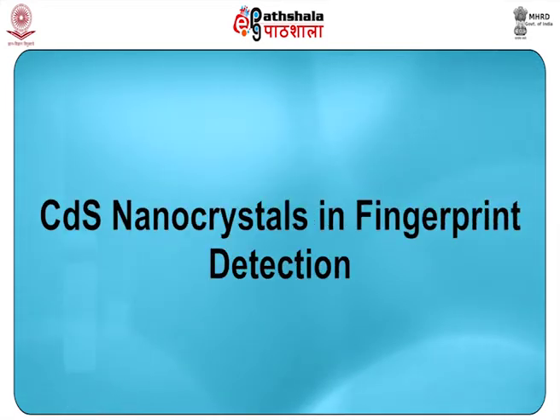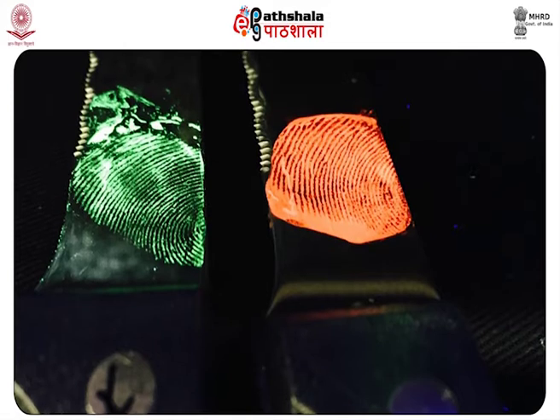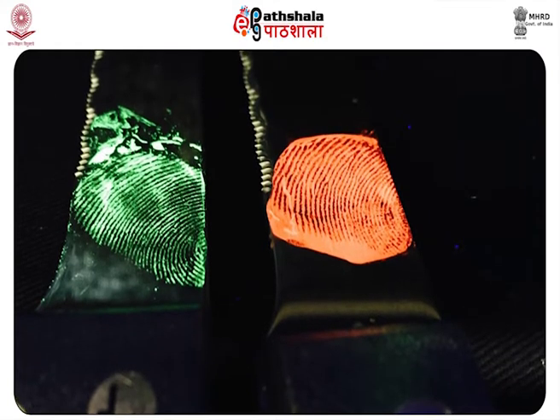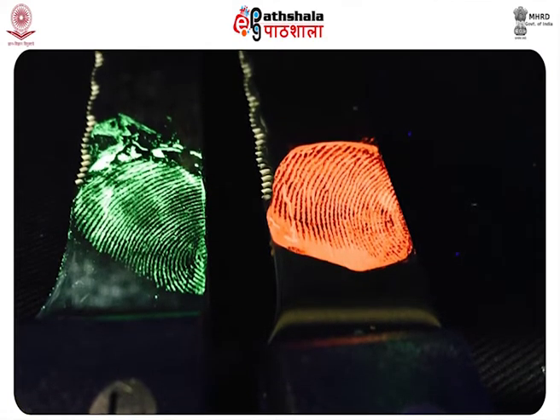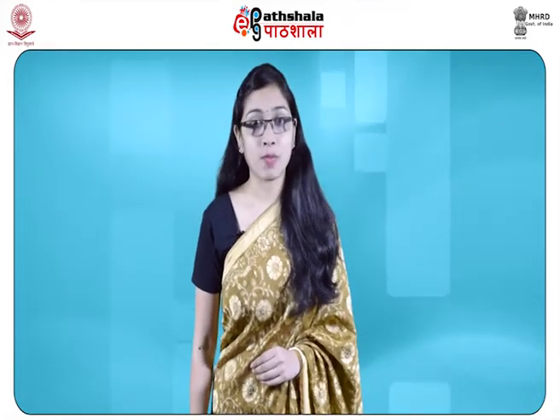Now, we will study cadmium sulfide nanocrystals in fingerprint detection. Photoluminescent semiconductor nanocrystals may be expected to be used for fingerprint detection in various ways, namely by incorporation into the dusting powder in a manner akin to fluorescent dyes, by blending with the magnetic powders, by staining, especially once the fingerprints have been exposed to cyanoacrylate ester or the cyanoacrylate fuming technique, or by chemically bonding to constituents of the fingerprint residues. In photoluminescence detection of fingerprints, the staining approach generally tends to be more effective, when applicable to the article under examination, than the dusting procedure.